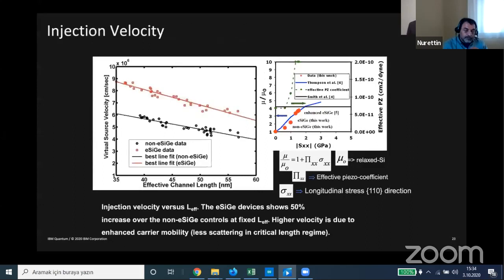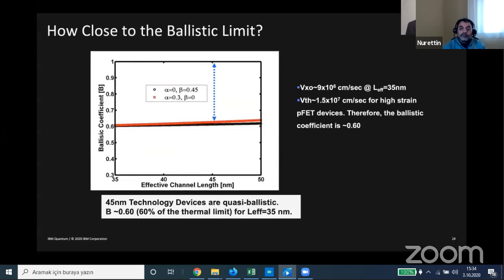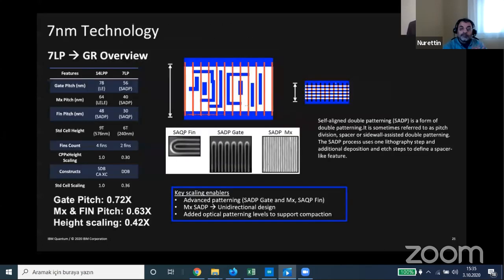So to measure this important metric of how ballistic we are, I characterized the injection velocity of strained silicon versus unstrained silicon. And I calculate at 35 nanometer gate length, the velocity is around 9e6 centimeter per second. Comparing this with the thermal limit of 1.5e7 for high strain PFETs, the conclusion was that the ballisticity is about 0.6. So we're about 60% of the thermal limit at 35 nanometer. In other words, there's still plenty of room for boosting mobility and reaping the gains in transistor performance. And indeed, we did that.